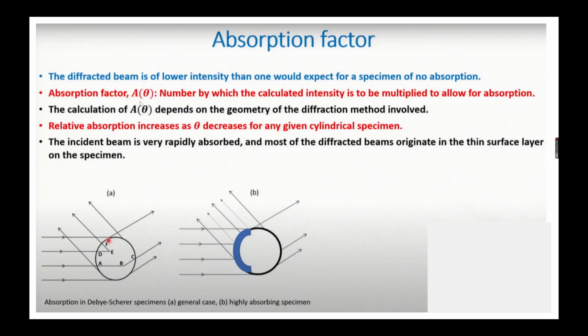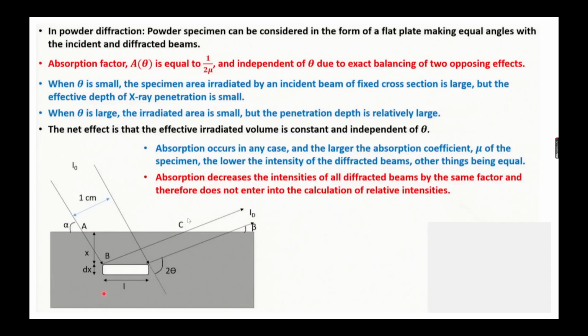So here it is saying that this calculation depends on the geometry of the diffraction method involved. So here this absorption factor A(2 theta) is equal to 1 upon 2 mu, and independent of theta. So it will not depend in any way on theta, which is Bragg's angle. It is only dependent on mu, proportional to 1 upon 2 mu, and does not depend on the theta value, due to exact balancing of two opposing effects.